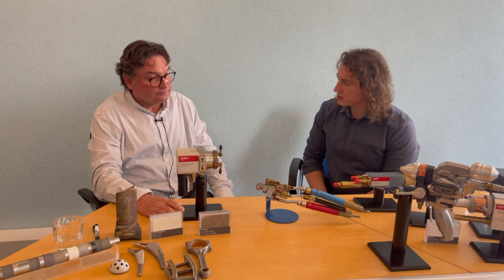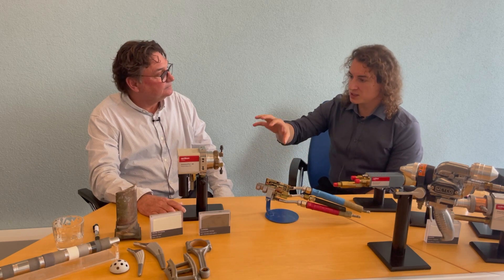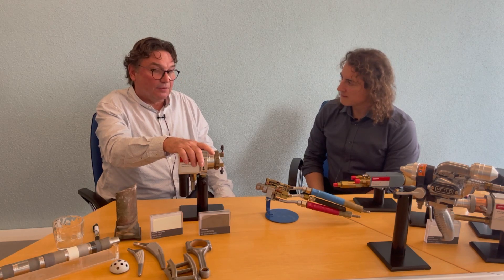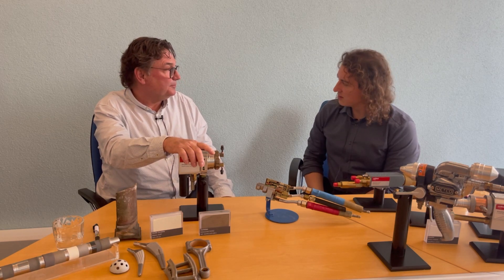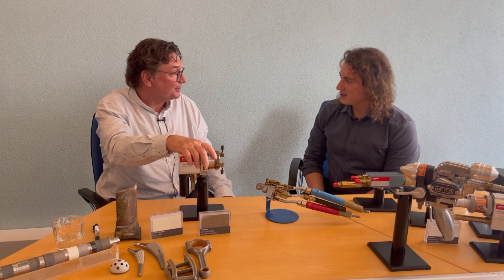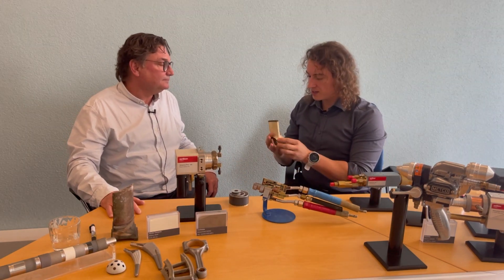Peter, what are the main applications where you see the benefits of the plasma process — what is the main direction where plasma technology is used in industry today? Mainly it's used for oxide ceramic coatings. All those cooking pans are sprayed with alumina mixed with titanium oxide, because it's the cheapest plasma coating you can do. So all dry-wear cooking pans or some rolls are coated using this alumina-titanium mixture.